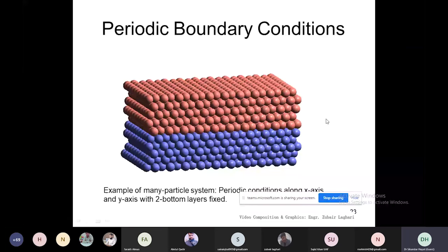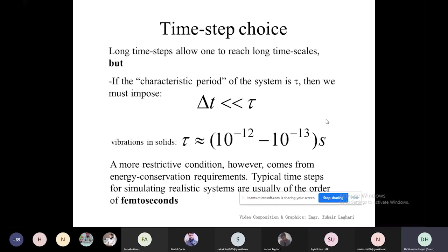For the purpose of creating a surface, we have to give the periodic boundary conditions in 2 dimensions, while in the surface direction we have to give some fixed boundaries so that no image is developed in that direction. Now, during the simulation, this is molecular dynamics, and we are going to focus on the dynamics or oscillations of the atoms.